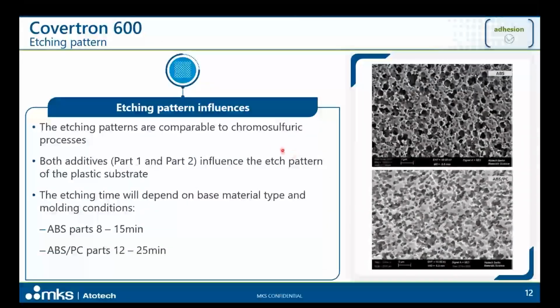As can be seen in these SEM pictures that you have on the screen, the pattern that we are able to create is really comparable to the sulfuric-chromic etching. The process, Covertron 600, works with two additives, the Covertron 600 Part 1 and Covertron 600 Part 2. Both of them will influence the etching pattern of the plastic substrate. So both are important to create what we are looking for.